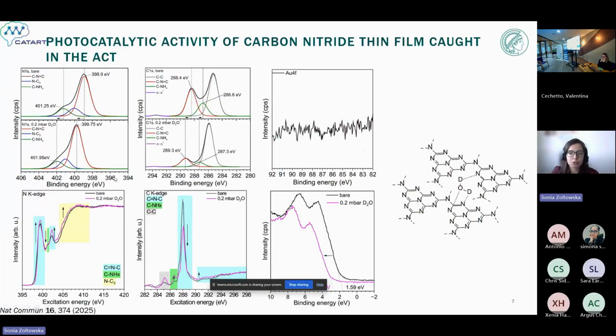And during the flowing of the water, we were measuring again the XPS spectra. And you can see that the absorption of water shifts the XPS features of the nitrogen core level and carbon core level towards higher binding energies, especially for nitrogen, which plays a role in the donation of electron density to form a hydrogen bond with heavy water. This behavior lowers the entire electron density of the surface layer of the semiconductor, and that's why we also see the shifts of the carbon core level features towards higher binding energies. Important to note here is that we couldn't measure the signal coming from gold, so we can exclude gold precipitation in the entire catalytic process.